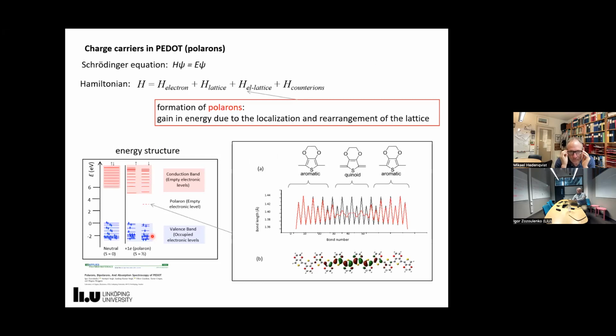Okay, so the origin of the charge carriers, as I said, is polarons, and this is the term which describes very strong interaction between electrons and the lattice. The lattice, I mean the polymer chain, is in principle very flexible, and because of the flexibility, it turns out that you can get a gain in energy if the electron charge is localized in some limited region of space. And you also have rearrangement of the character of the bonds. So for example, in this picture, you can see a chain of PEDOT with one polaron localized here.